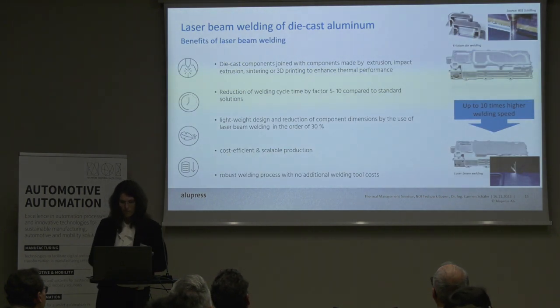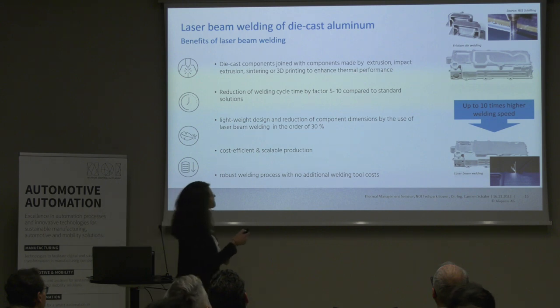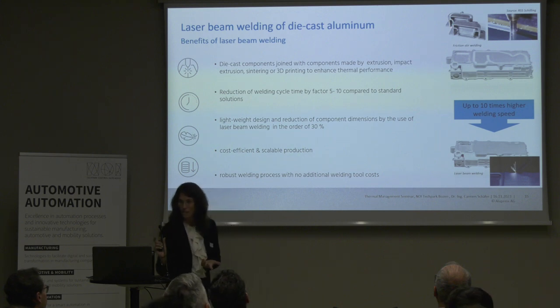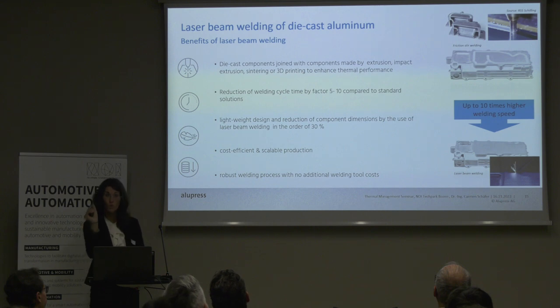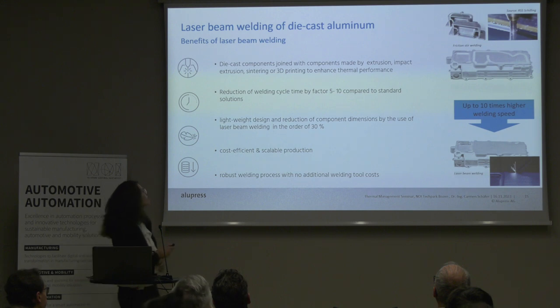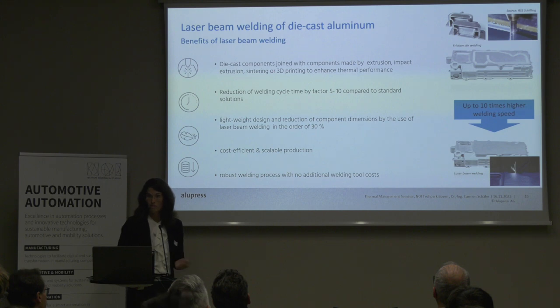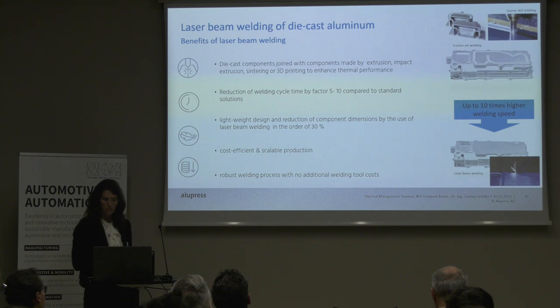So what are the benefits of laser beam welding? I have mentioned friction stir welding already. This is this process. Most of you know it. This is laser welding. And you see here already it's a huge difference. The width is 8 millimeters for friction stir welding, and I go down to 2 millimeters width in laser beam welding, with the same properties for these applications. I can also combine die casting with whatever other process, for example, with other aluminum. And by changing here from friction stir to laser beam welding, I have a weight reduction of 30%. And this is more cost efficient. This process, as I said, is 5 to 10 times faster.